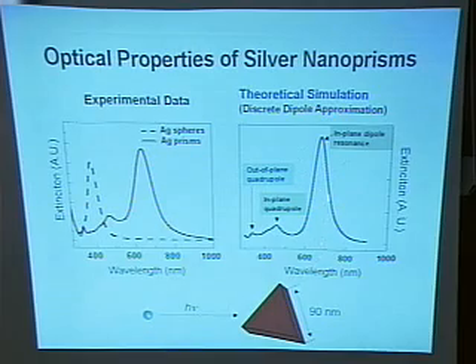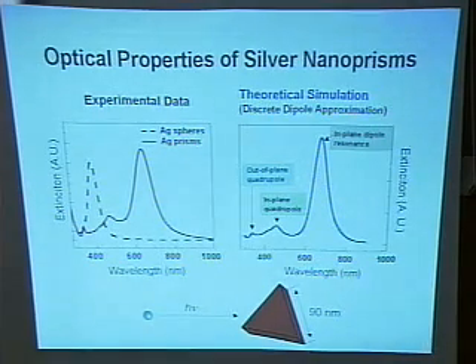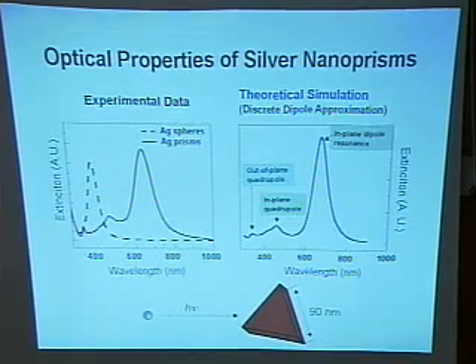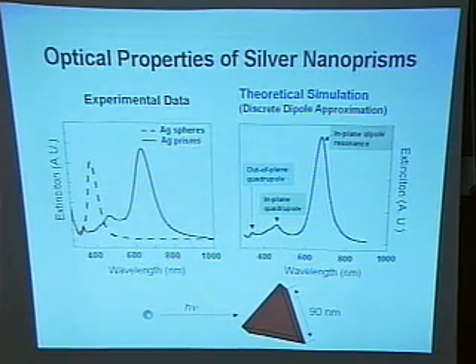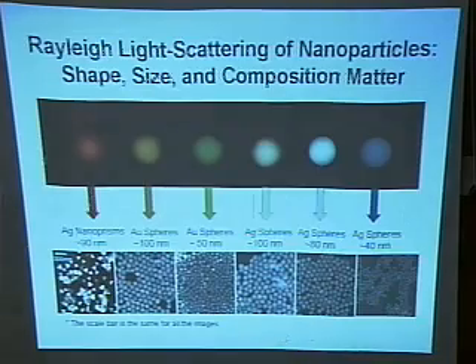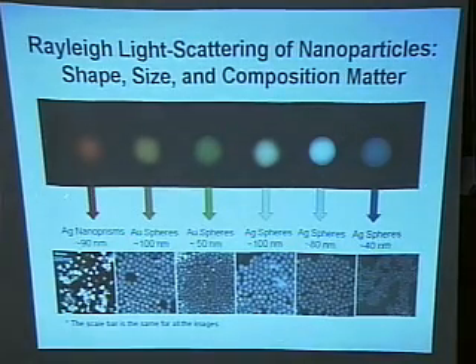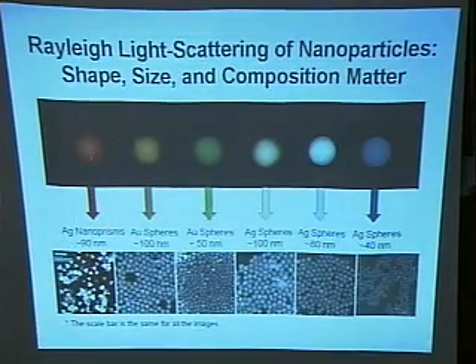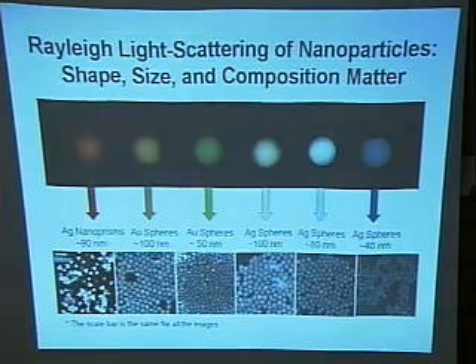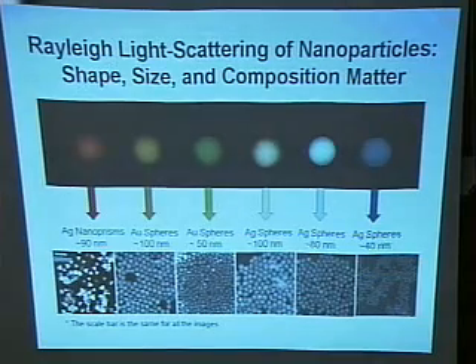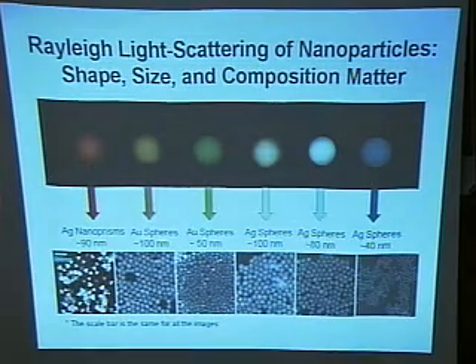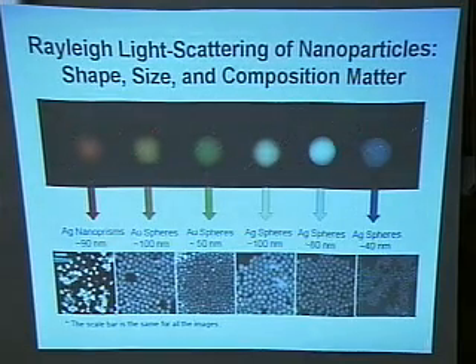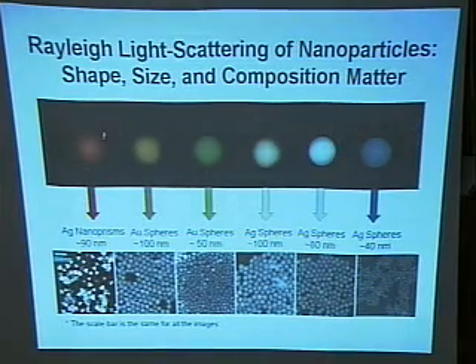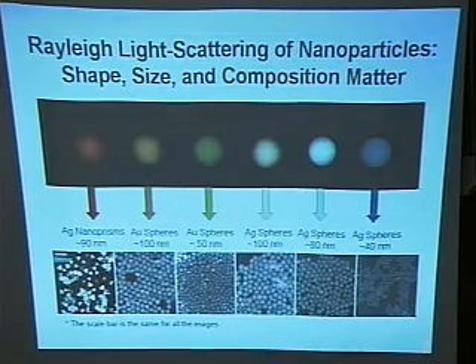Because of the in-plane dipole resonance at 670 nanometers, they should scatter light in red. So if you combine silver or gold particles with different sizes, you can build a beautiful scattering rainbow. So this is silver nanoprisms. And this is fundamentally important. You tune the size and shape and combinations, you can get different scattering light. Technologically important, you can use each of these particles as a biomarker. So say if you functionalize 6 different oligonucleotide probes, then you can simultaneously detect 6 probes in one solution.